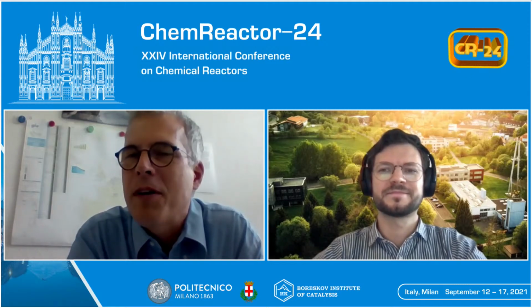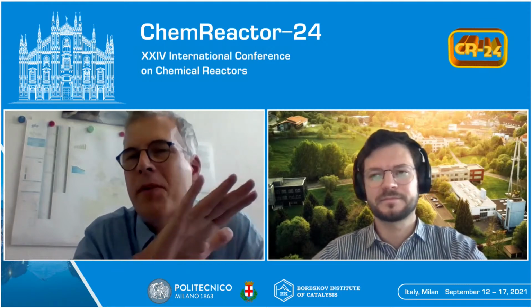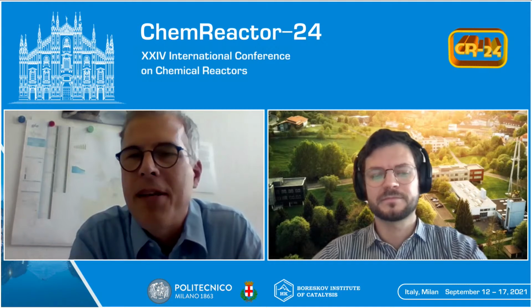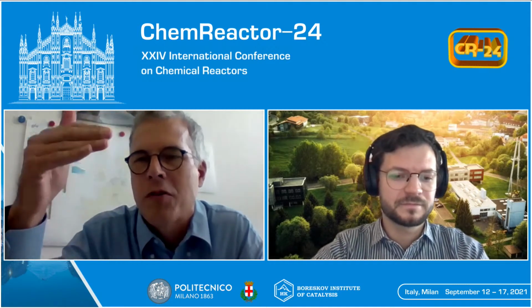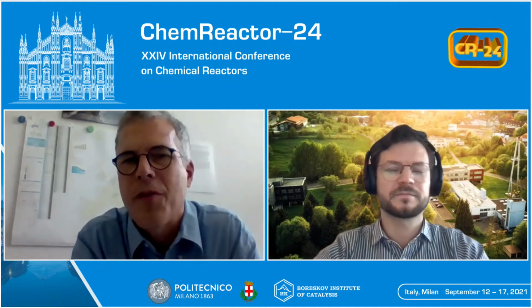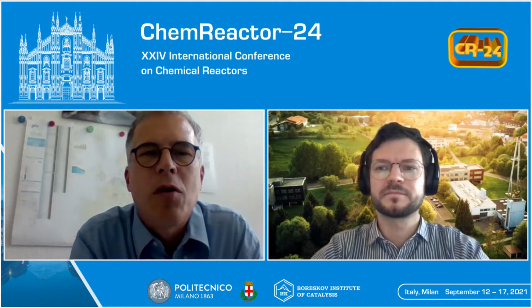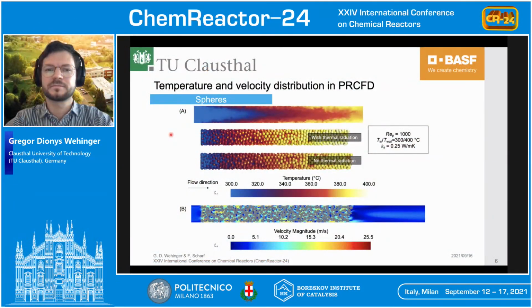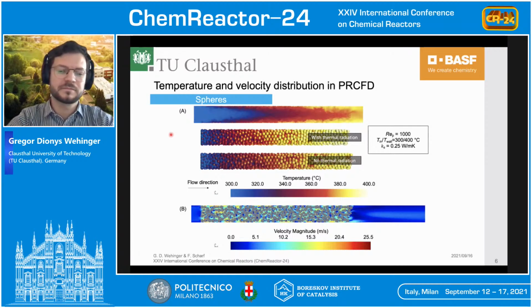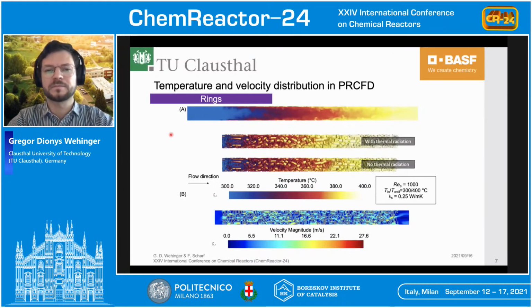And maybe to warm up, I start with one. Actually, when you showed these graphs on where we see the temperature distribution over the particles, I had the feeling that you always showed with radiation, without radiation. And if I look at the spheres, then the difference between with and without is not that strong. But actually, if you go to the rings, it was, in my eyes, a stronger effect where we see earlier the onset of that phase. For example, where you see the complete cross section being already yellow, that is most probably 2 centimeters earlier. So I have an idea of why that is, but maybe could you comment on that one?